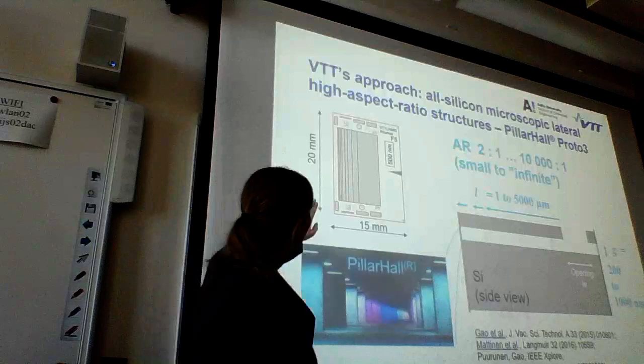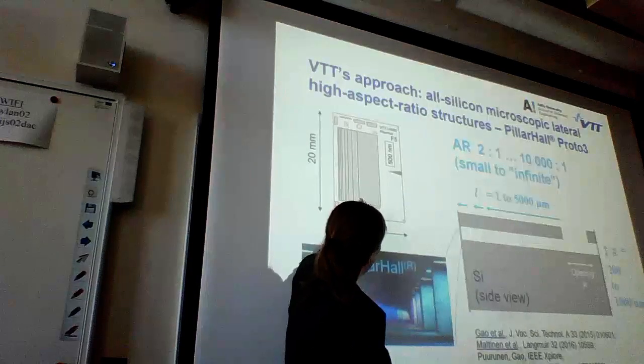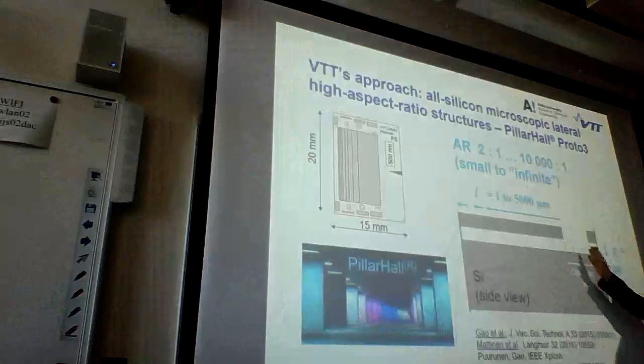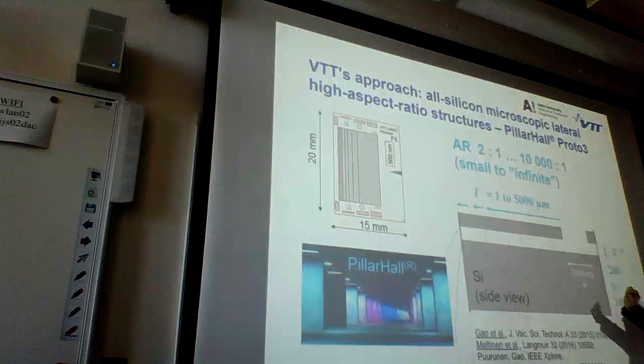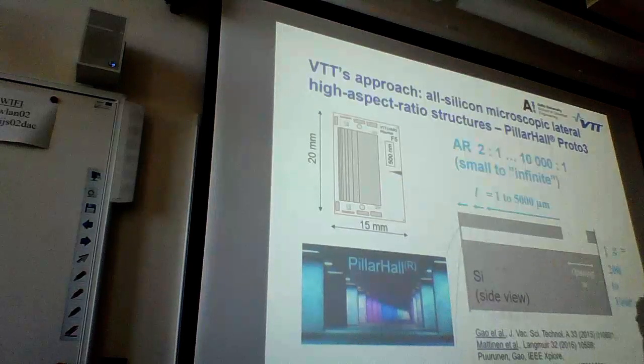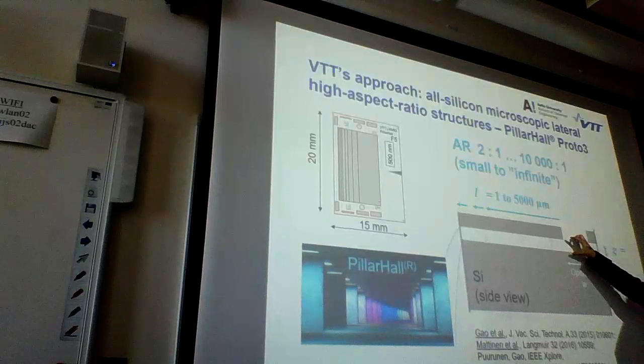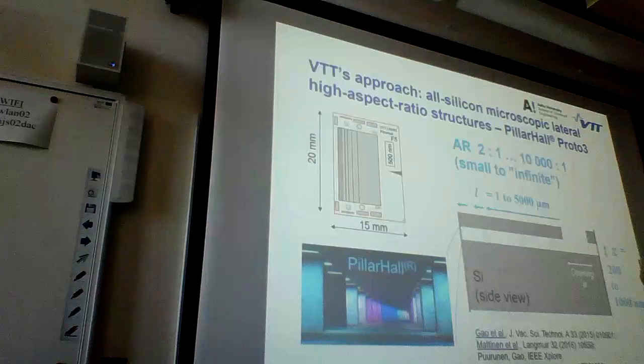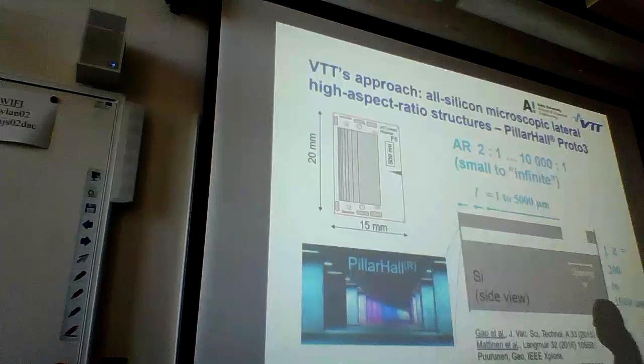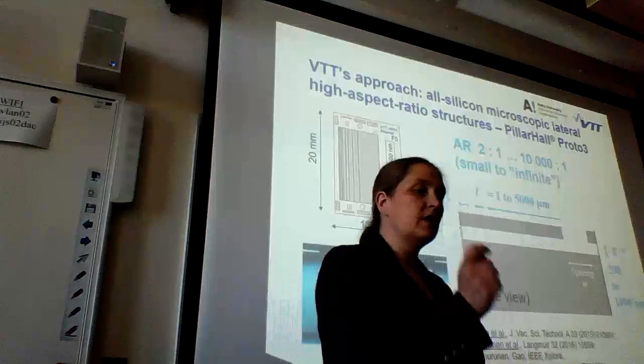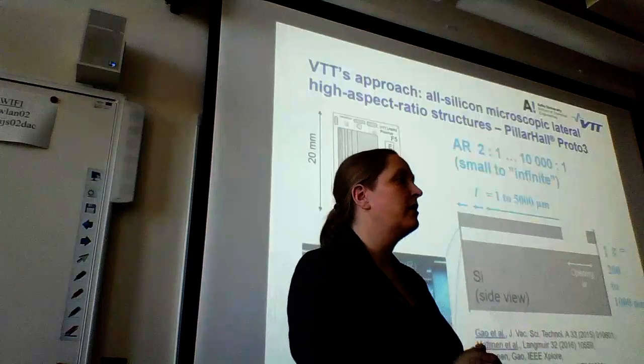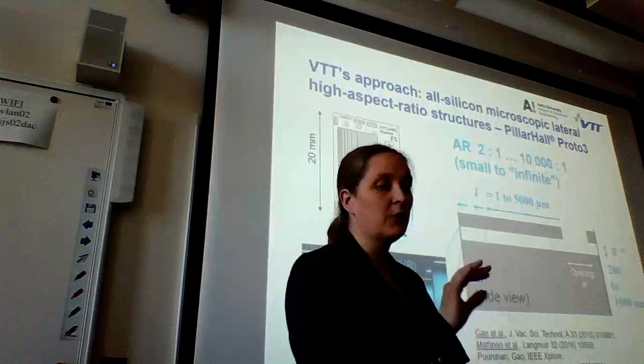So they have membranes which have one side open, and they look like this. Sometimes they are mirrored. Well, the biggest one is not mirrored, it's open only on one side. So it's a membrane that is supported by pillars. And there is a gap of very controlled height underneath. It's typically 500 nanometers. I see that I should write it here. And this is all the information. 500 nanometers, and at the moment we are making tests with 100 and 2000 nanometers too. So 500 nanometers, making it a microscopic structure so that the flows inside are corresponding to the ones that you typically have in microelectronic industry. So you have molecular flow at typical ALD conditions.